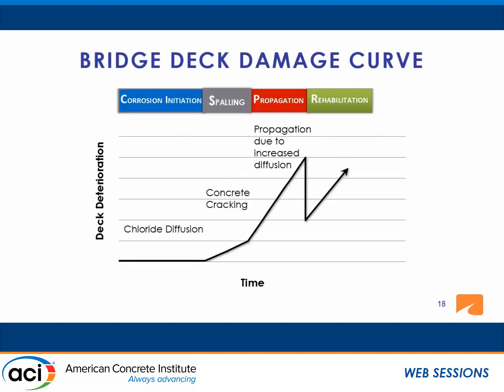And moving on to the service life prediction, this is a simplification of the life cycle of a bridge deck. We have the chloride diffusion happening starting from the day of the first de-icing salt application. Once they accumulate up to a threshold chloride value, corrosion initiates, and then once sufficient corrosion byproducts accumulate inside, once it exerts enough force to crack the concrete, you see cracks and spalls on the surface.